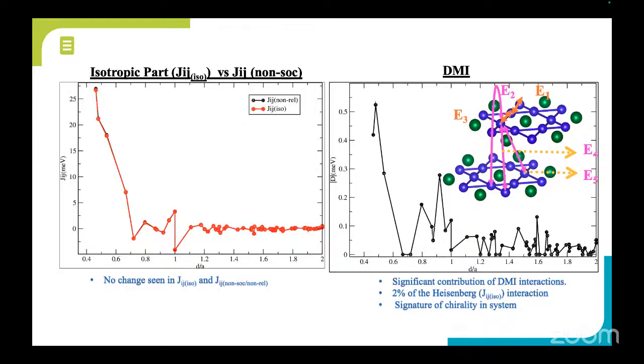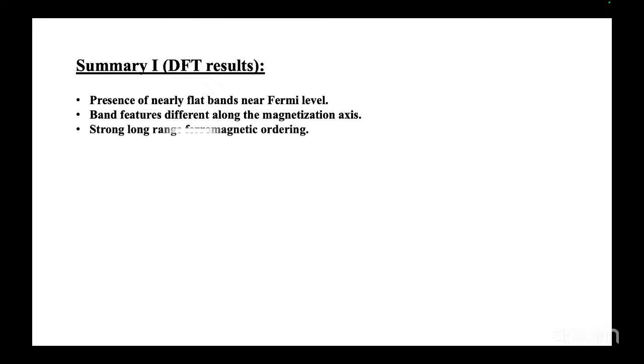So it gave us an idea that the DMI interactions are present in the system, and the interplanar DMI interactions are more than the intraplanar ones for the first and second neighbor interactions. Further, I would like to summarize the first part, the DFT: we see the presence of nearly flat bands near the Fermi surfaces. The band features are quite different when we look at different magnetization axes, and we see a strong long-range ferromagnetic ordering in the system.